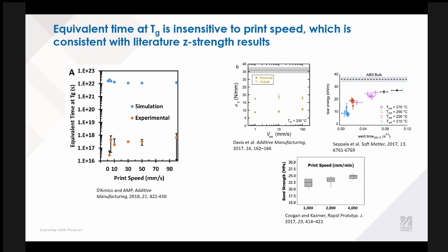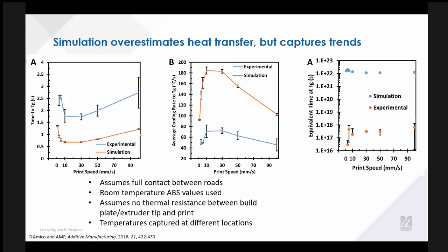And this is because even though we have a longer time to TG out at these ranges, the effect of the higher temperatures has such a larger weight than the temperatures that are closer to TG.